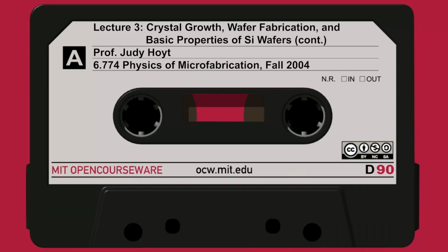So it's extremely important. If you have more than that, your charge is going to leak out faster and your DRAM's not going to work. So it's very important to keep these impurity concentrations low for that reason. What are these traps associated with? Trap density scales with the density of certain bad actors, and we'll talk next time about who these bad actors are in silicon. Impurities such as heavy metals, gold, transition metals like copper, iron, nickel, a lot of these turn out to be traps, deep levels that destroy the lifetime. But just to give you a rule of thumb, you need to be in the ppb range or lower.